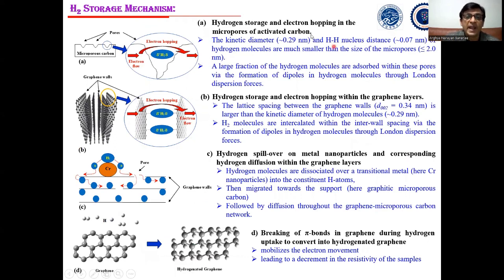Now, this hydrogen storage mechanism is a fourfold mechanism. Generally, hydrogen storage and electron hopping in the micropores of activated carbon is one reason. The kinetic diameter of the H-H nuclear distance is 0.07 nanometer, whereas the pore dimension is around 2 nanometer or less. Therefore, a large fraction of hydrogen molecules are adsorbed within these pores via formation of dipoles in hydrogen molecules through London dispersion forces. Similarly, in this graphitic network also, hydrogen storage occurs via this dipole formation. And because of this dipole formation, the electron hopping increases, and as the electron hopping increases, the resistivity decreases.